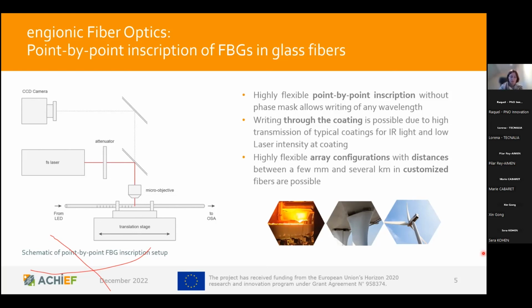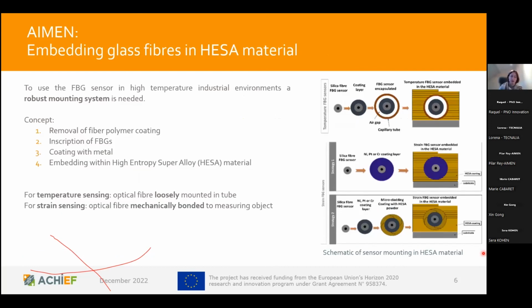When we discussed together with AIMEN how to best embed the fiber optic sensors in the HESA material, this is the proposed route that we came up with in the beginning. So first, we thought we would have to remove the polymer coating that usually is around commercial fibers to protect the fiber and make it not as brittle, inscribe our fiber Bragg grating structures into it, subsequently coat the fiber with metal for good thermal conductivity, and also to protect the fiber again at the high temperatures where polymer materials no longer would work, they would just burn away. And in the last step, embed these sensors in the high entropy superalloy material.